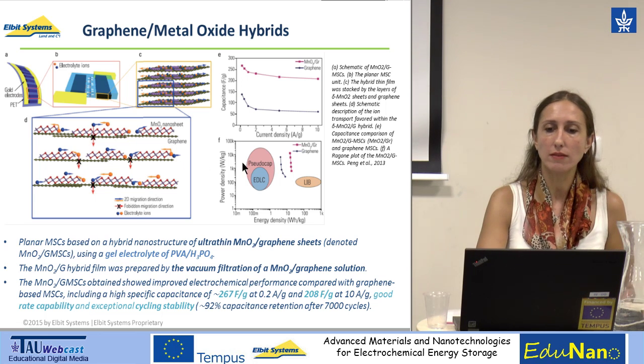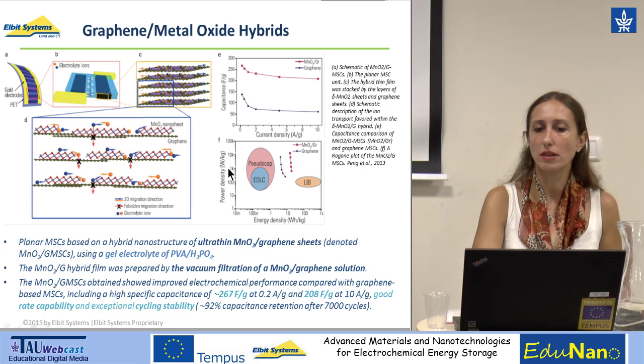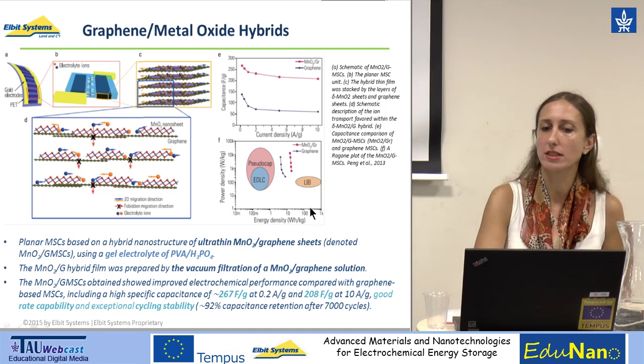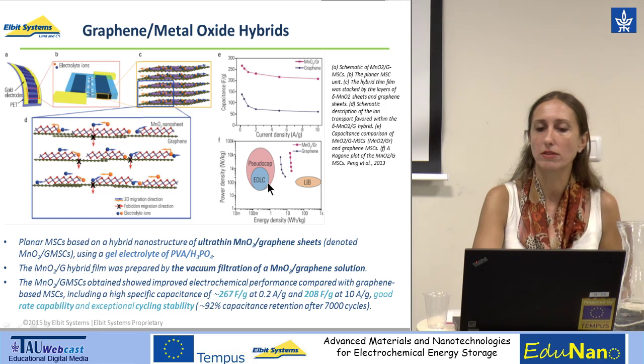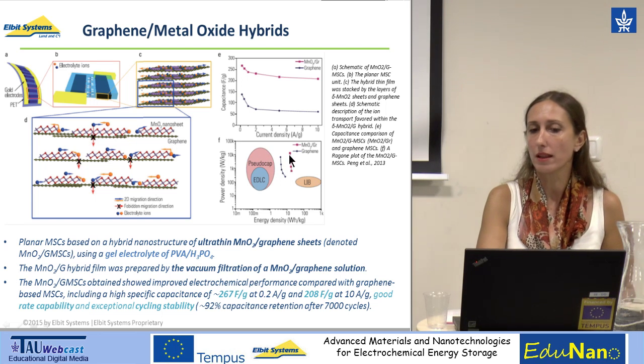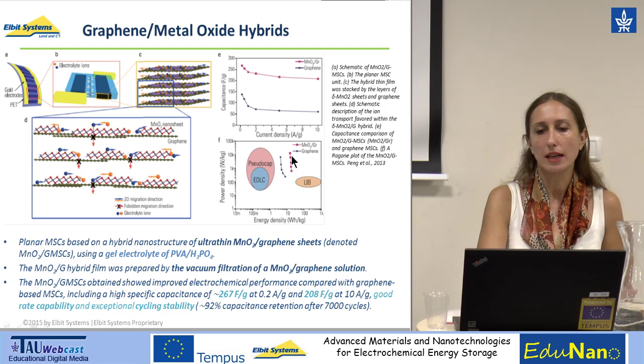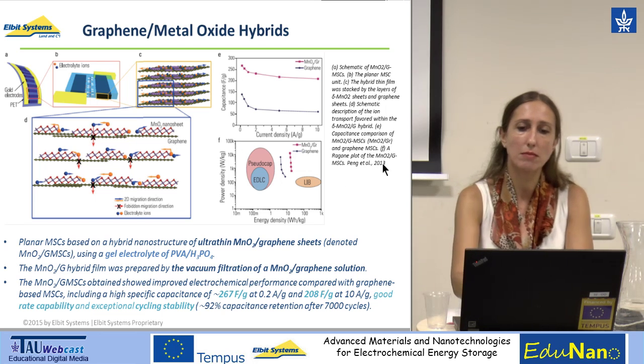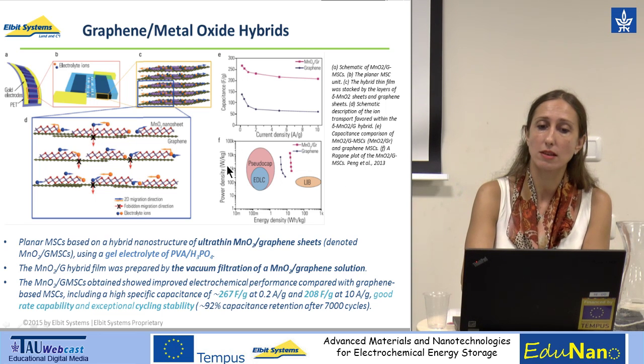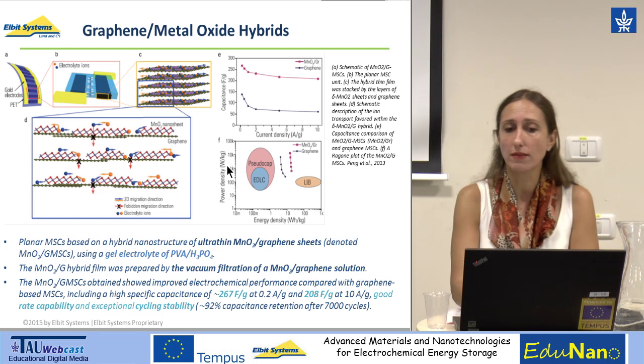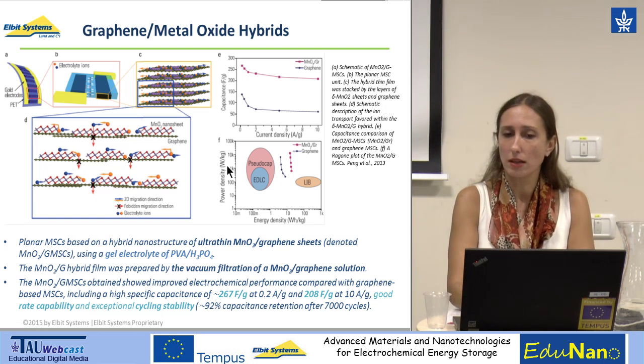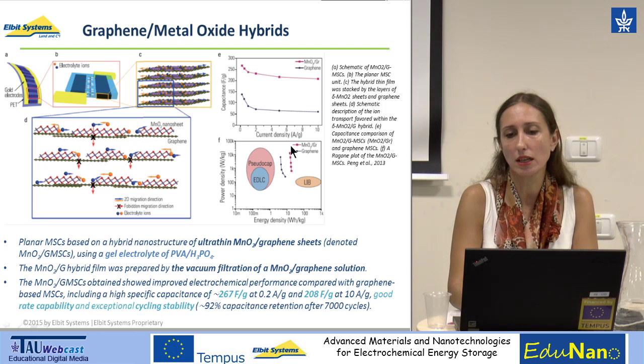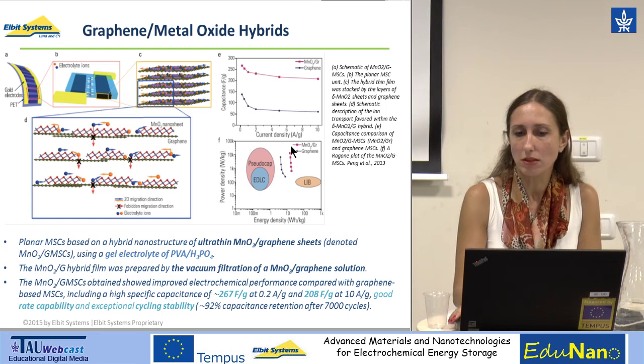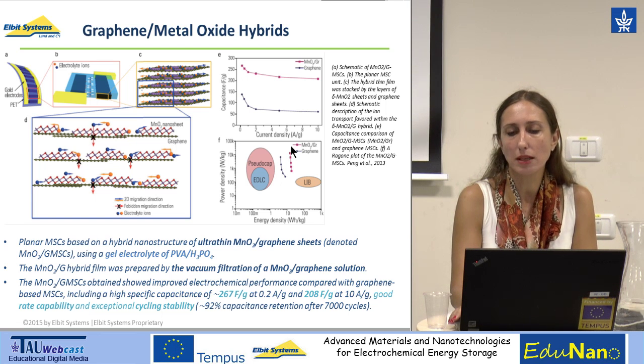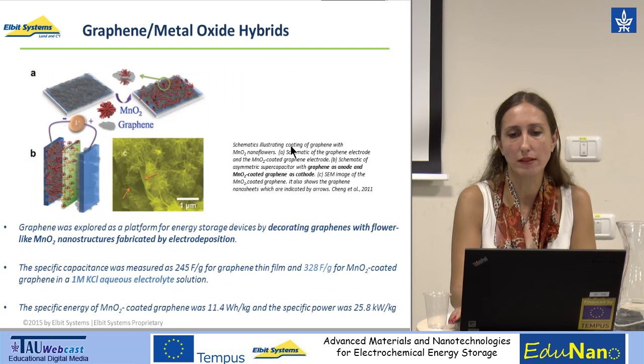And what makes it very attractive? This is clearly shown in these Ragone plots of power density versus energy density, where you have the EDLCs, the known electrical double layer capacitors, the pseudocapacitors, and the lithium-ion batteries. They are somewhere here. So we are talking about energy densities in the range of 10 watt-hour per kilogram, with power densities of 10,000 watt per kilogram, so 10 kilowatt per kilogram. Very nice values, actually. So it is a very promising route for being implemented and shown in a real device.